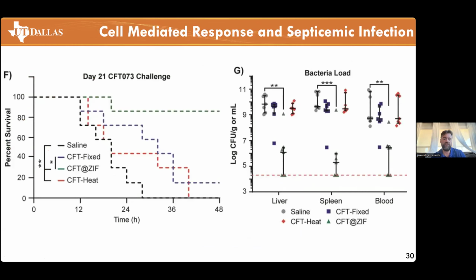Once these animals have been inoculated, we then challenge them. We give them a lethal dose of that pathogenic bacteria, and we see what happens. Completely naive mice are dead within a day. They cannot fight off this infection. The fixed and the heat-treated both do fairly poorly. You do get some prolongation of life, but not significantly. Whereas in the case of the ZIF encapsulated formulation, we essentially see very, very good survival, something that is very hard to do.